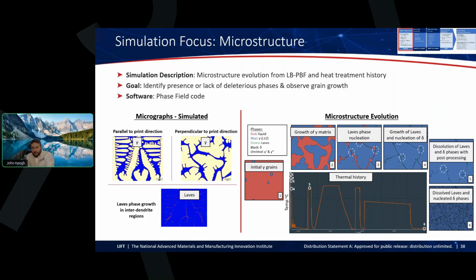I'll draw your attention to the bottom right there, that black thermal history trace. That is actually a real trace of our additively manufactured build. You can see some of the thermal cycling early on through the build, taking the build then out into stress relief, and then a subsequent set of heat treatments and annealing. So that's the full post-solidification thermal history of those parts. We then took that thermal history and coupled it with our phase diagram, CALPHAD models, and the phase field code, and we were able to simulate our microstructure evolution through the powder bed, heat treatment, and all that. Begin to identify the presence or lack of deleterious phases, observe and predict grain growth, and so on.